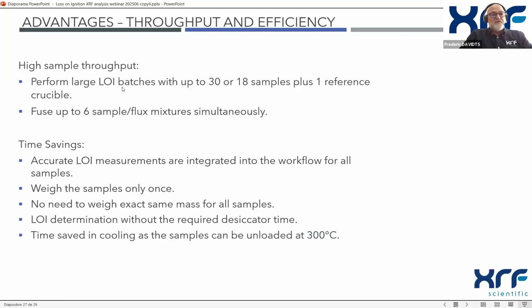So the big advantage of this technique is the throughput and the efficiency. High throughput because, of course, you can process large LOI batches: 30 if you use the liners, or 18 if you use the platinum-gold crucibles directly. And after, you process the 6 fused beads in the XRFuse, and we save time because the LOI measurements are integrated in the workflow.